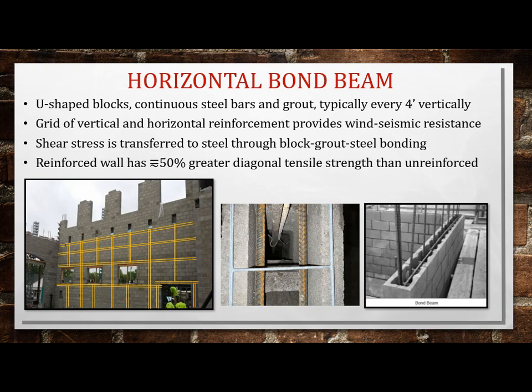Another critical element, the horizontal bond beam. Again, it's a U-shaped block. It's continuous horizontal steel bars. Lap splice is critical. Typically, these are every 4 foot vertically. And so what the picture on the left shows is the grid work of the vertical grouted cells and horizontal bond beams, and this is what provides the wind and seismic resistance of your wall. The shear stress is transferred to the steel through the bond strength between the block, grout, and steel. And so what I've read during this is that a reinforced wall has approximately 50% greater diagonal tensile strength than an unreinforced wall.